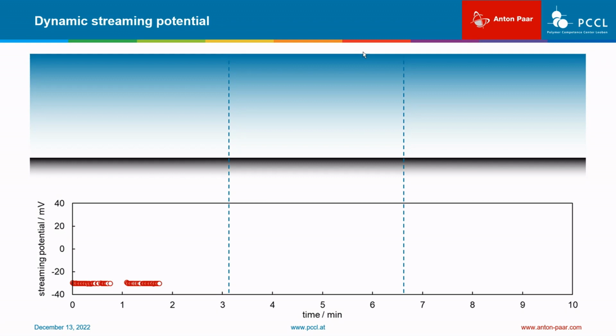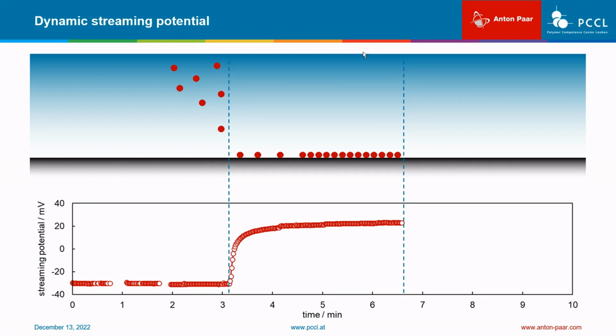And we may repeat this baseline measurement several times. We then add a certain concentration of the adsorbate to the aqueous solution, and we realize a change in the streaming potential once the solute approaches the solid material surface and decides to adsorb on that surface. After achieving adsorption equilibrium, we may exchange the buffer solution again and observe another change in the streaming potential that indicates the contributions of reversible versus irreversible adsorption.